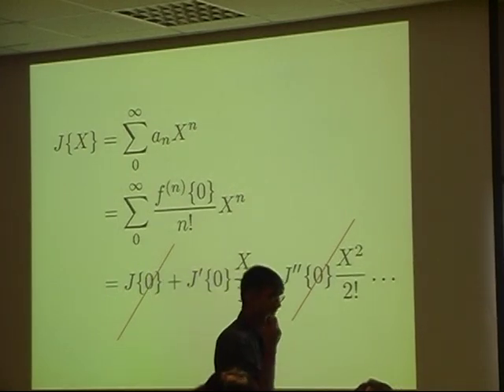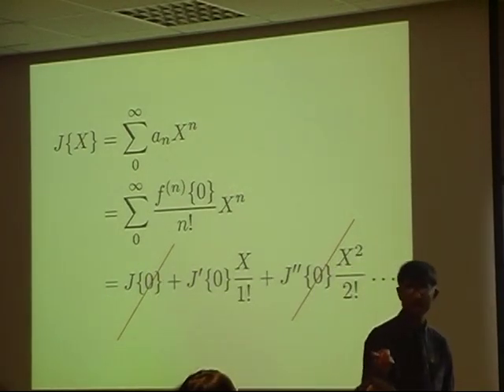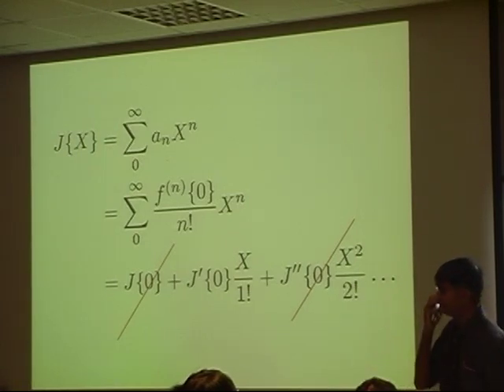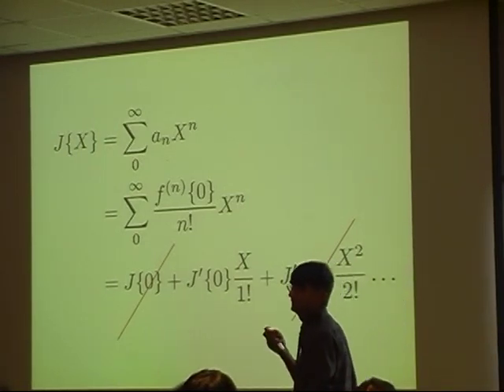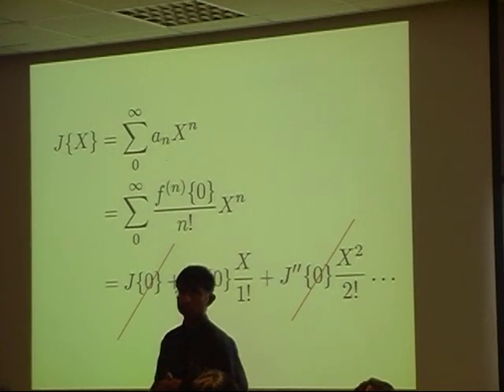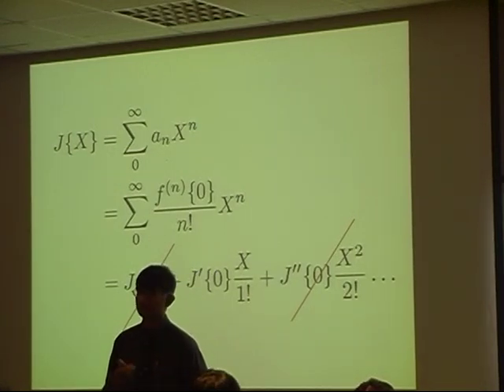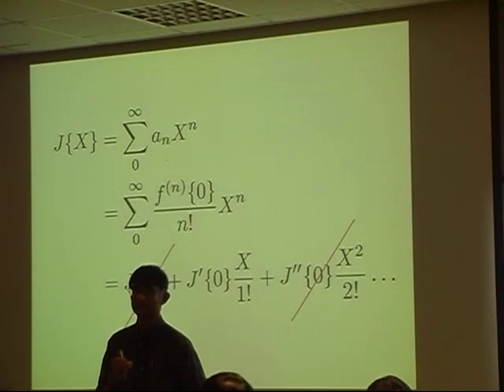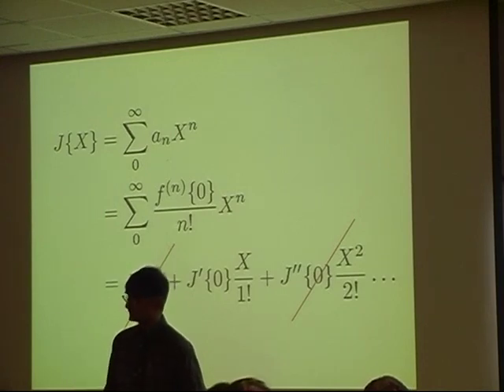Similarly, if you have a very large gradient of free energy, then maybe the diffusion flux will not be proportional to that. And in fact, that is the case, that at very large gradients, Fick's law no longer applies. And the diffusion coefficient becomes a function of the gradient itself.